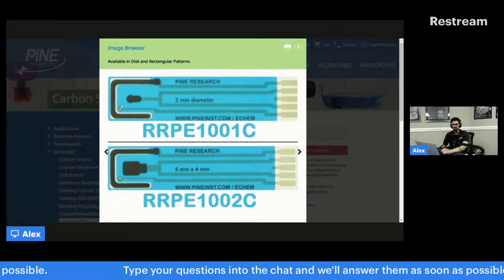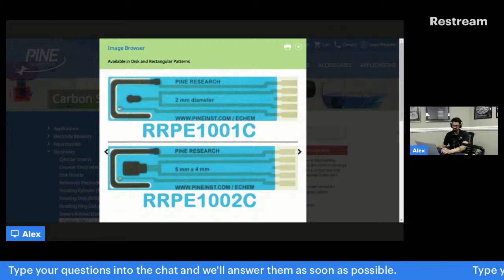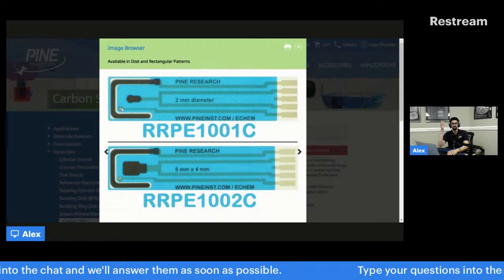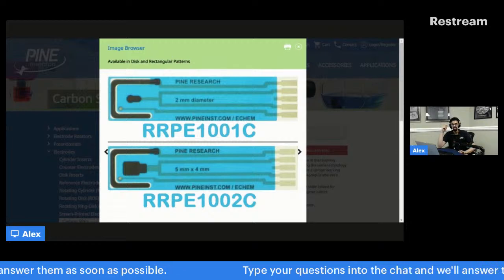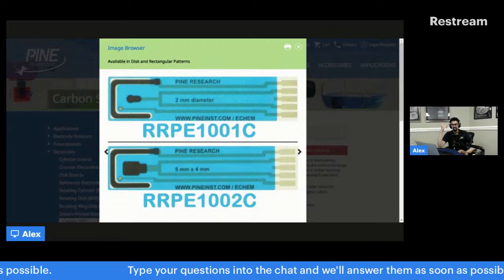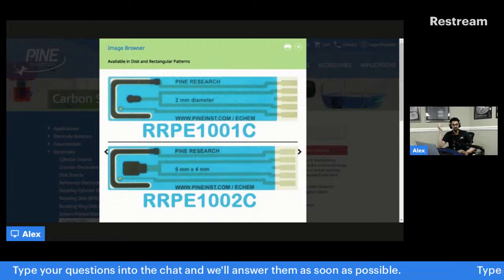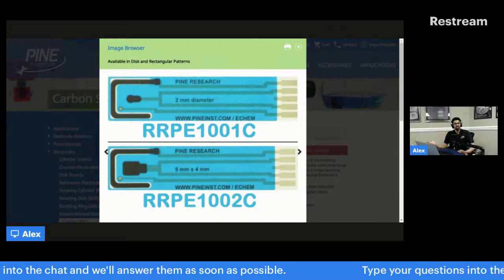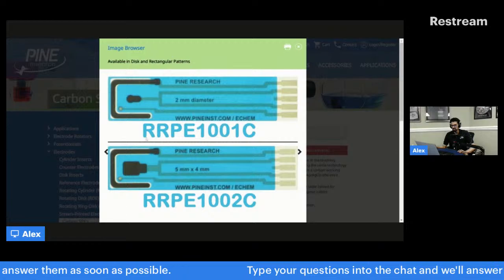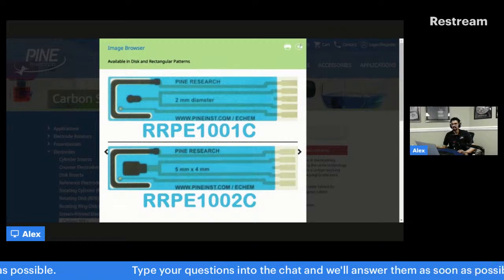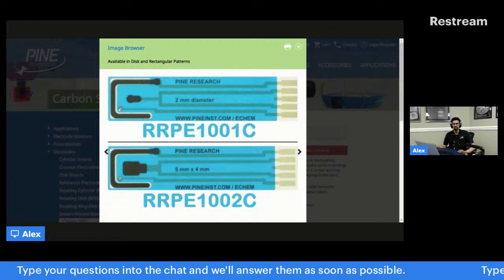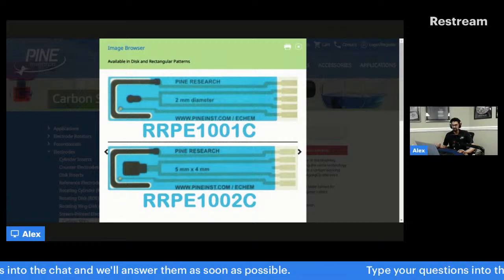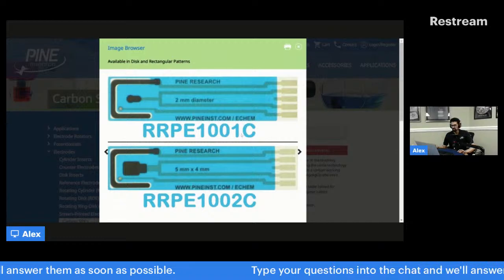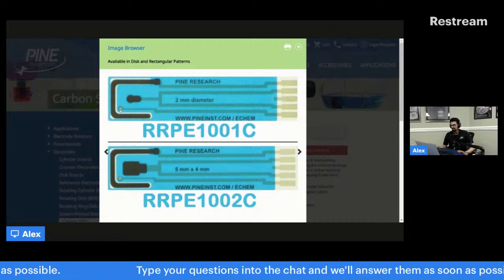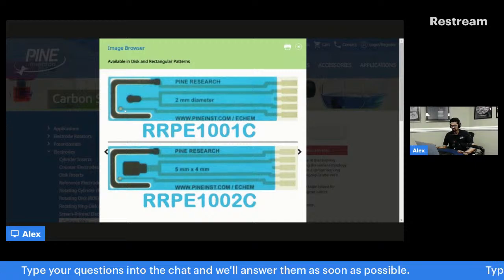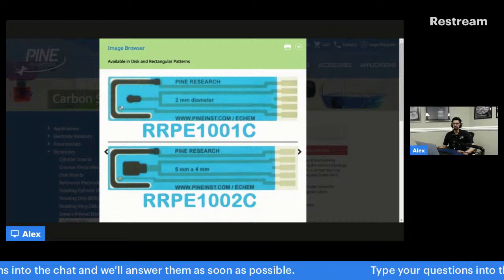The reason why we might recommend using a separate reference electrode is that this silver chloride dot, its potential will shift and change as a function of the analyte or the electrolyte concentration. So it can change during the experiment, and it's not very well characterized. If you're using a non-aqueous system, you might not even want to use these because it'll dissolve. The blue polymer binder actually dissolves the insulator.